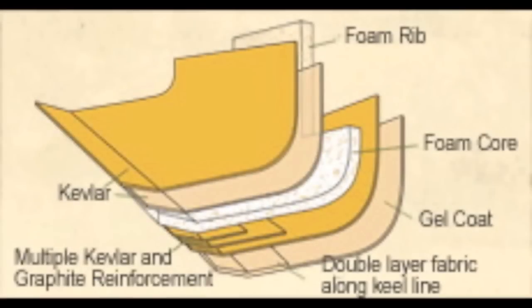Basically, the core of the layup is multiple layers of Kevlar cloth. There is a thin layer of glass on the outside to better bond to the gel coat and also provide abrasion resistance and ease of repair. After that, multiple layers of Kevlar. Then you go into the foam core, which has a diamond shape, which gives you stiffness, saves weight, considerable amount of weight, because you're replacing cloth by foam, and you're also reducing resin because the foam doesn't absorb resin.